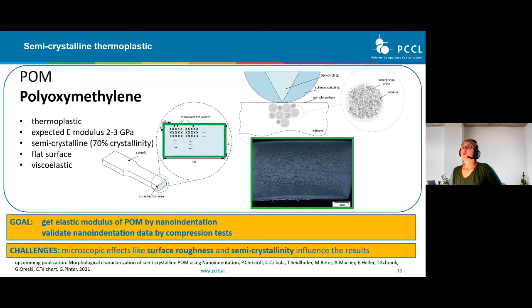Next, I want to show you the investigation of a semicrystalline thermoplastic, and here we chose POM as a model. POM is a thermoplastic and has an expected elastic modulus between 2 and 3 gigapascal. It's semi-crystalline and has a rather high crystallinity of 70%. The sample also has a flat surface and is viscoelastic.